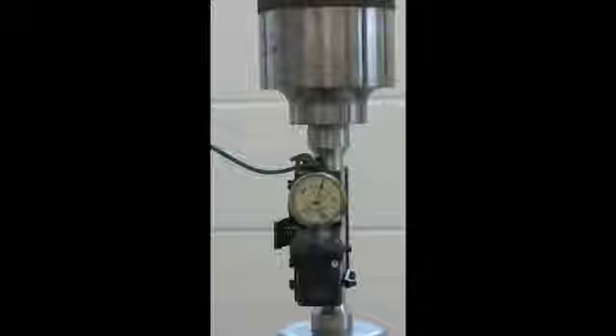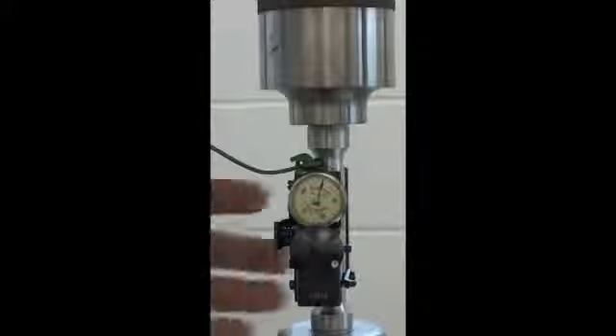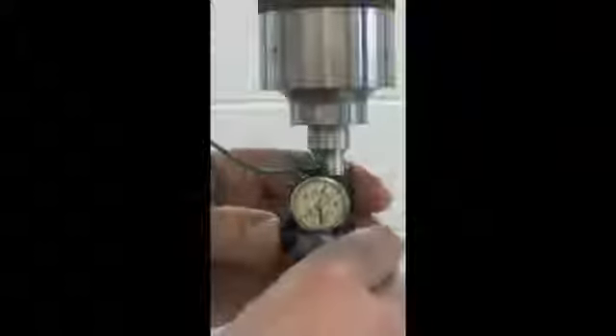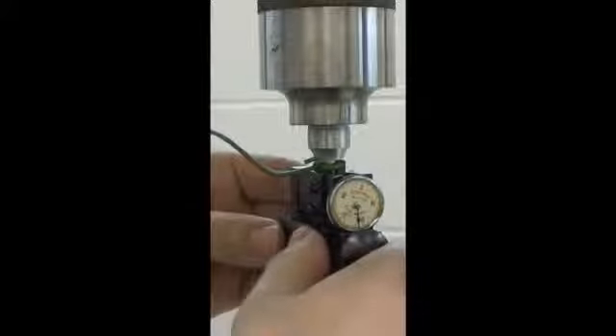Now we want to remove the extensometer after it reaches its maximum range to avoid any damage. That's done by pushing the release clip and removing the device. The aluminum specimen broke at 15,300 pounds load. So from here we can remove the specimen from the fixturing.